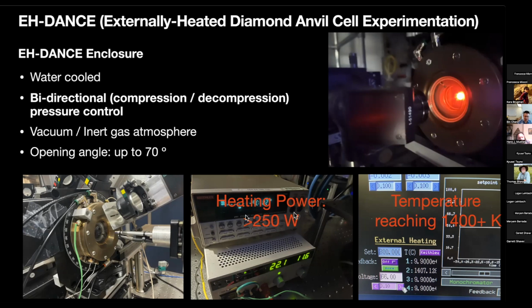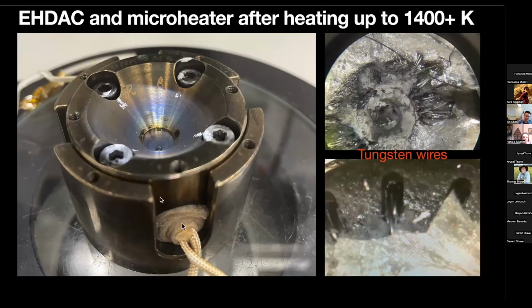And then last year, we made a few attempts at heating the sample to more than 1400 Kelvin by applying around 250 watts. This picture shows the light that comes out from the heater in the externally heated diamond cell, which also indicates that the heater has a very high temperature. After we took out the externally heated diamond cell, the diamond was intact, and as you can see, the tungsten wires that we used to reach this high temperature also appear to be intact after heating to 1400 Kelvin.